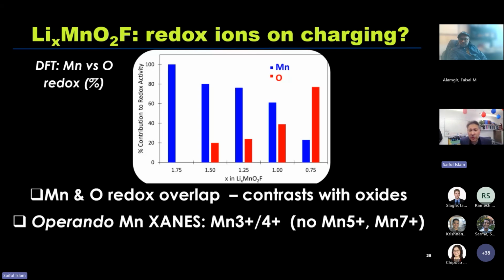So let me explain what I'm showing you here. Up on the y-axis is the percentage contribution to the overall redox activity as a function of charge. So I'm showing you 1.75 lithium on the left and then 0.75 lithium on the right. So we're extracting 1 lithium per formula unit, charging the material, lithium extraction. The blue is manganese redox and the red is oxygen redox. So you can see straight away on the left that at the start of charge, it's dominated by manganese redox.